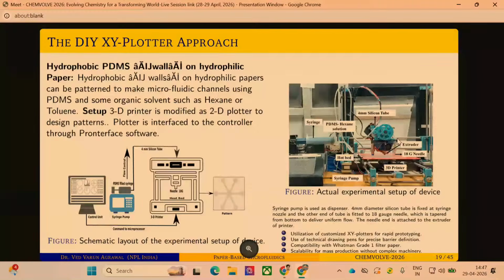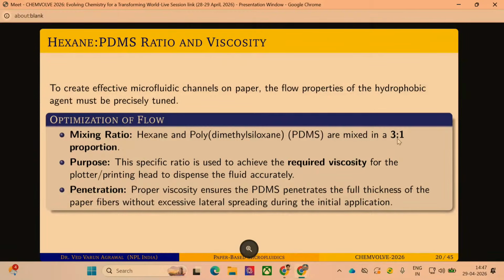It can go up to 110 degrees Celsius, but we were using a moderate temperature. When we are writing, we were actually curing the ink as well. So this is our schematic. And we mixed hexane to PDMS in the ratio of 3:1, and the idea was to have the ratio of hexane higher in this because we wanted to reduce viscosity to a large extent, because otherwise it will not flow in that tubing, which later on we had changed, but this is an initial work. So to ensure the proper viscosity, this is an optimized value.